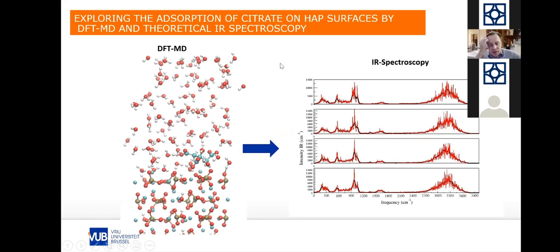So this is the last part that I would like to show, and it is in fact an application of molecular dynamics. We have an interface here: this is our hydroxyapatite, I have the water, and we've put a complexing agent here, citrate. And the question is, can we obtain from our molecular dynamics a spectroscopic fingerprint, an infrared spectrum, for example? This is very important because it gives us a direct possibility to compare with the experiment. We have a spectrum on which we can stick a molecular model. So this is very powerful.